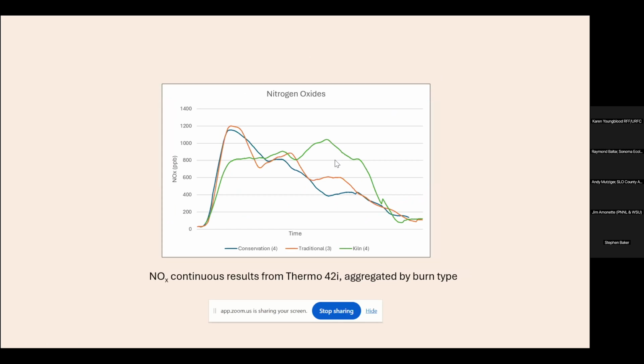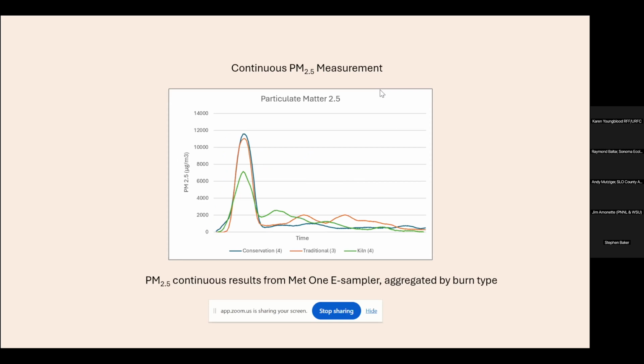Nitrogen oxides are usually associated with high efficiency flaming combustion. So again, they peak during the high fuel consumption and then start to go down as the fire transitions from flaming to a mixed phase of smoldering and flaming together. The kiln stayed higher, I think, because the kiln reaches a steady state and doesn't really go to a smoldering phase. It kind of goes to a steady state, more high efficiency kind of phase. Particulate matter follows kind of the same pattern.